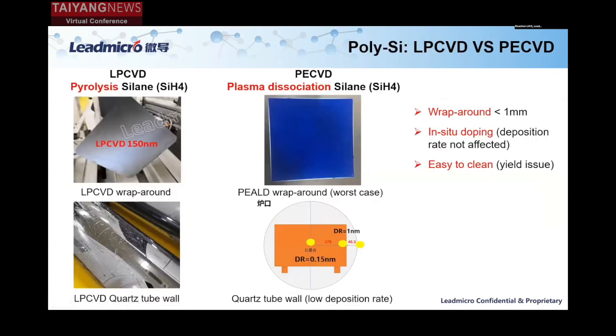Second one, for polysilicon, is a comparison between the LPCVD versus the PECVD method. The LPCVD method is well known for its drawbacks: the wraparound and also the operating cost, the quartz tube depositions. The PECVD method, in contrast, can resolve all the bottlenecks faced by the LPCVD method. Firstly, you can see the wraparound. The white color at the edge is less than 1 millimeter. The second advantage is that the plasma enables in situ doping without affecting the deposition rate. You still can do the in situ doping at a high deposition rate. And due to this in situ doping, it also resolves the yield issue. It's very easy to clean.